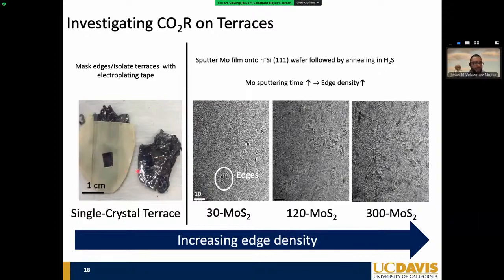single crystal synthesis. Because this is a layered structure, each of the layers within the single crystal are weakly bound by van der Waals forces. So we could take hints from graphene and do mechanical exfoliation and expose a fresh surface by just using the Scotch tape method. So we use the Scotch tape method to expose as many terraces and perhaps fewer edges to the electrochemical environment. And then what you're seeing here is what we call electroplating tape.